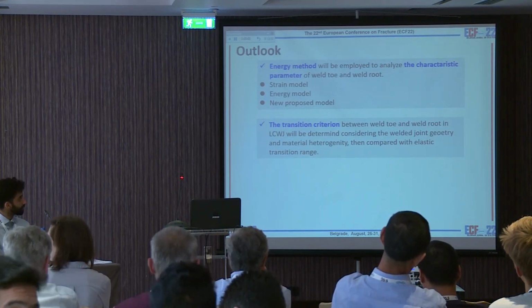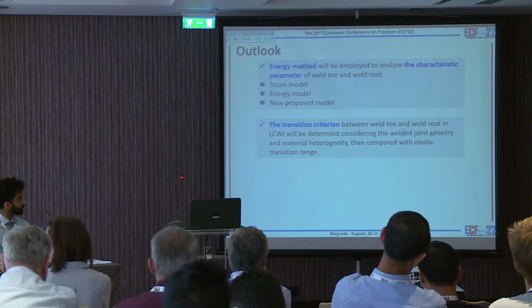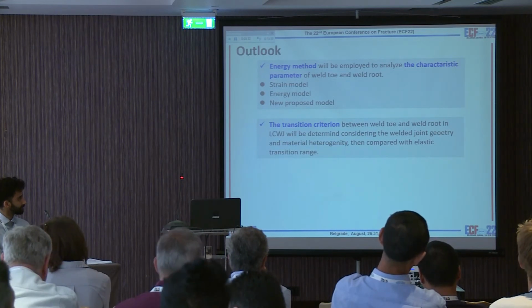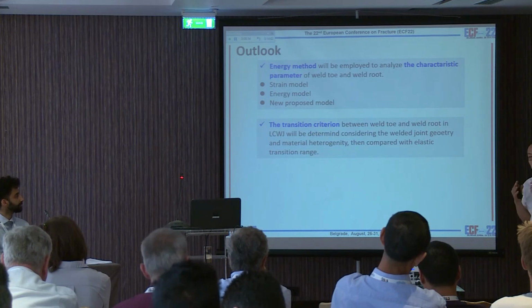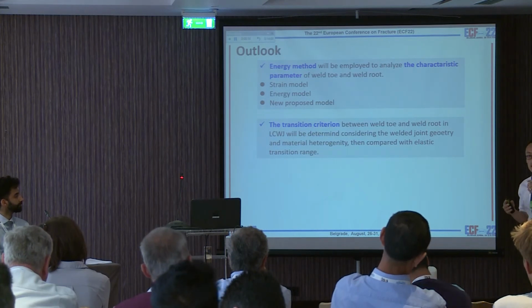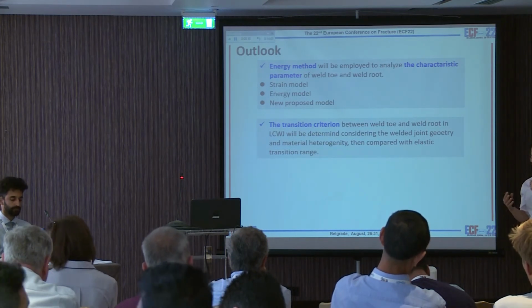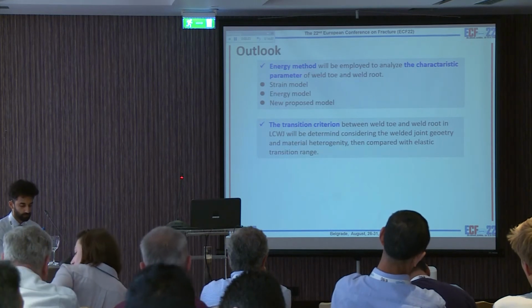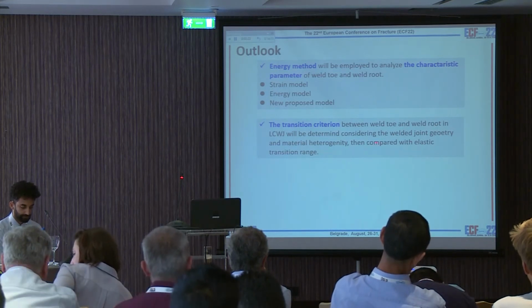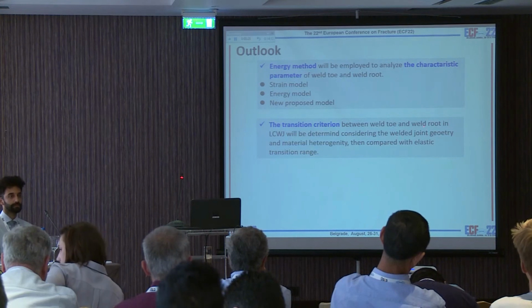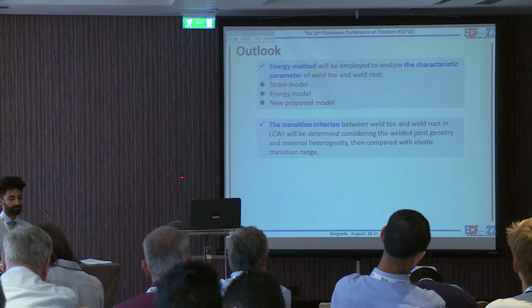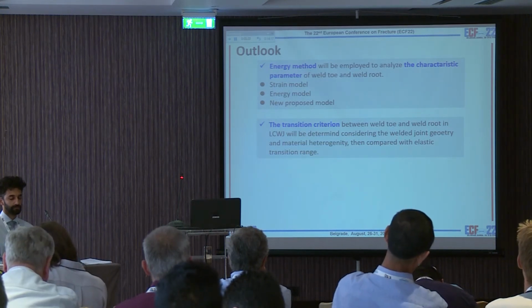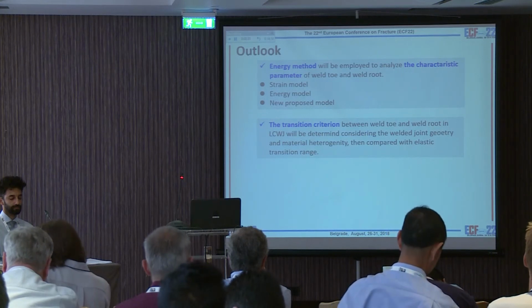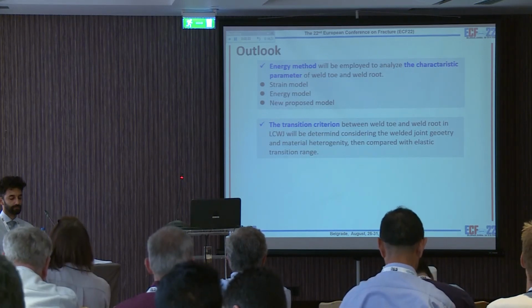And then we're using the energy method to analyze the characterized parameter of welded toe and welded root and compare the different models, and finally we get the transition zone between the welded root and the welded toe. And finally, we will compare it with the elastic transition range.